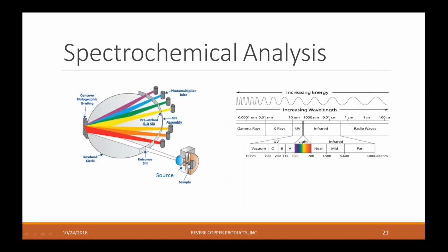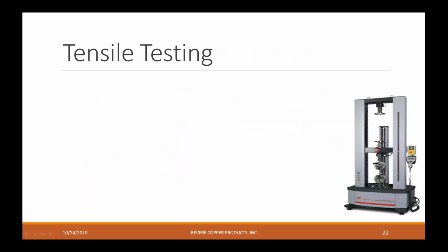The first thing, we always test for chemistry. I mentioned earlier, it's got to be pure. There's an ASTM standard that states what the purity level needs to be, but it has to be pure in order to meet those properties for the anneals to work and for the rolls to work. So we do a spectrochemical analysis to make sure that copper meets requirements.